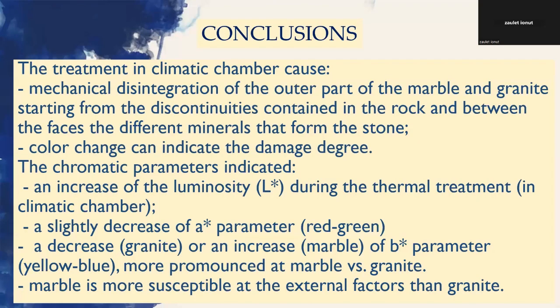In conclusion, the treatment in the climatic chamber causes mechanical disintegration of the outer part of the marble and granite, starting from the discontinuities contained in the rock and between the different minerals of the stone. Color change can indicate the damage degree.